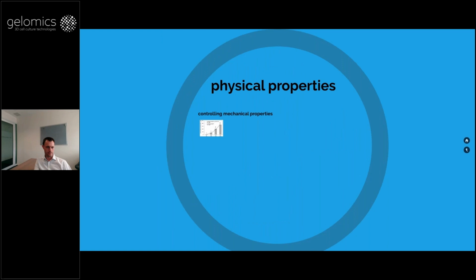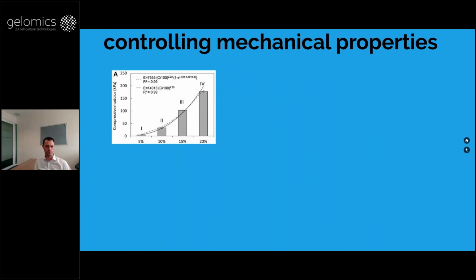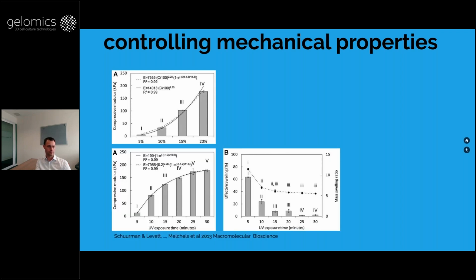So we started looking into GelMA and mechanical properties. When you use a gel for 3D cell culture, the mechanical properties, and particularly the stiffness or compressive modulus, which is stiffness under compression, is quite an important parameter. It has quite a big influence on cell behavior. So we looked at the influence of the concentration of GelMA as well as exposure time. Stiffness would increase with concentration and with prolonged exposure to UV, which obviously is dependent on the system you use, like your photoinitiator concentration and your light source as well.